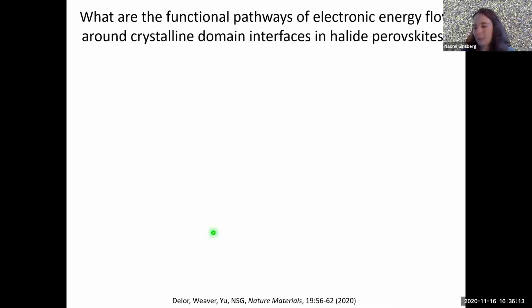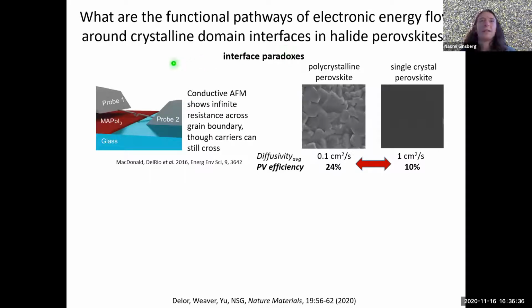But I do want to spend most of my time talking about stroboscat, and this particular example relating to these halide perovskites. We're interested to know the functional pathways for how the charge carriers flow when there are crystalline domain interfaces. Okay, so the problem is really this: charge carriers are known to travel between different crystalline domains, but conductive AFM measurements have shown that there's an infinite resistivity across the interfaces. And also, another paradox is that the efficiency of photovoltaics that employ polycrystalline perovskites is higher than the single crystalline perovskites.